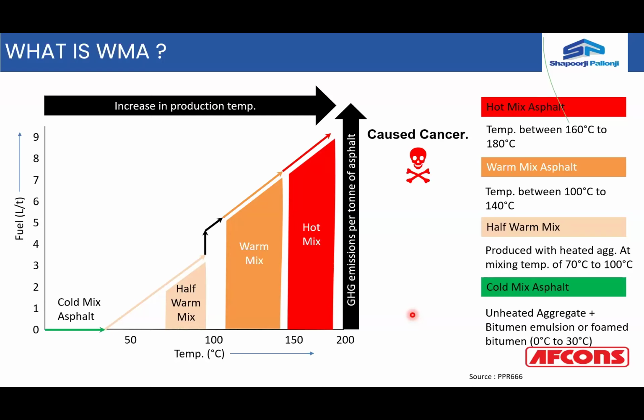So VG30, VG40, or if you are using a PG grade or a PMB grade, the mix temperature changes a little depending upon the softening point of that particular mix. This is what I have understood as far as the asphalt is concerned. So the idea is, how do you control the mix temperature without compromising on the mix quality or the mix workability? Now, to ensure that the mix is workable even at a low temperature, the technology which came up is not new in the global industry, but of course in India, it started popping up since 2010.